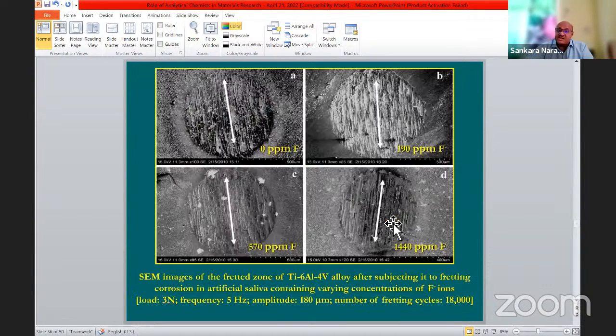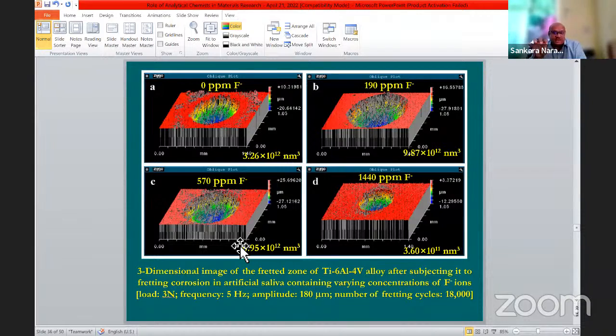But it is very difficult to predict such a thing based only on SEM. We have to use multiple analytical techniques to understand the fretting corrosion behavior, because it is normally not visible to the human eye. The damaged area is restricted to about 200 to 300 microns, and you cannot see this damage with the naked eye. We have to use a scanning electron microscope. But even with scanning electron microscopy, we cannot understand the mechanism or predict which concentration is crucial. Using a surface profilometer, we could clearly understand the mechanism.